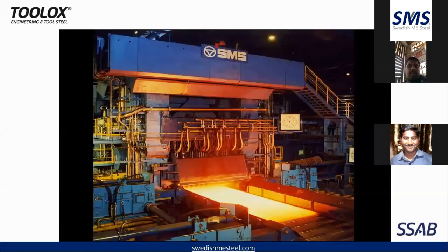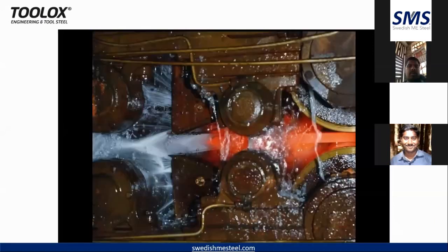These are the slabs which come out of the rolling mill. And this is where the entire R&D of this pre-hardened steel lies. As you can see, the steel here is water quenched. It comes out in red hot condition, and it turns into room temperature within a matter of seconds. For different thicknesses of plate, the quantity of water quenched at different angles determines the different properties of the metal that is achieved. So this is the exact R&D of the material.